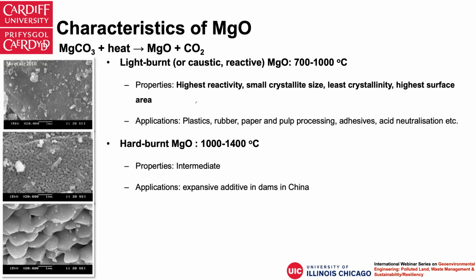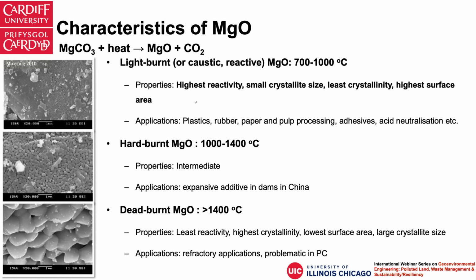And if you increase the temperature to 1400 degrees C, you get hard burn magnesia. This grade of magnesia is mainly, almost exclusively, used in China as an expansive additive to compensate for the shrinkage of concrete. If you further increase the calcination temperature, the crystalline size keeps increasing and the surface area keeps decreasing, as you can see from these figures, and you have a much lower reactivity. So the key idea in this slide is that if you increase the temperature, you get much lower reactivity. Much lower reactivity usually means a much lower dissolution rate and a much lower reaction rate with other phases. So that is the conventional way of categorizing magnesia.